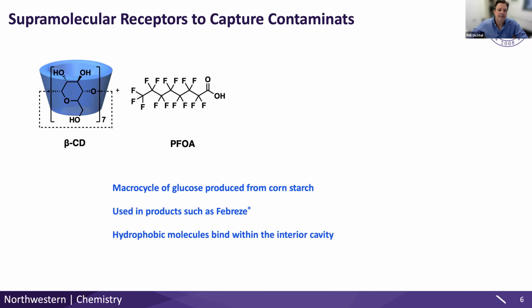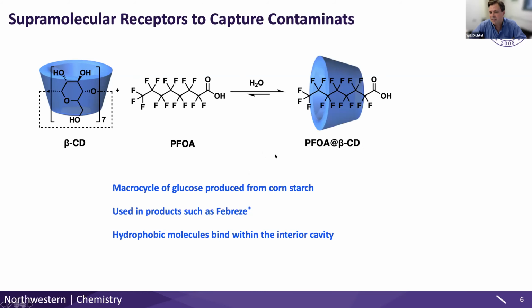So I've drawn the molecule PFOA here. What is special about cyclodextrin and this cup-like shape of it is that the inside of the cup is kind of greasy, and the outside of the cup really likes to be in water. These OH groups interact with H2O quite well. And so it's kind of this little tiny nano environment that is a great binding site for molecules that have a water-hating component, such as the fluoroalkyl part of these forever chemicals like PFOA. They just dock right into the cup, and they fit nearly perfectly down at the molecular level, so they can be very nice and specific and avoid fouling by natural organic matter.